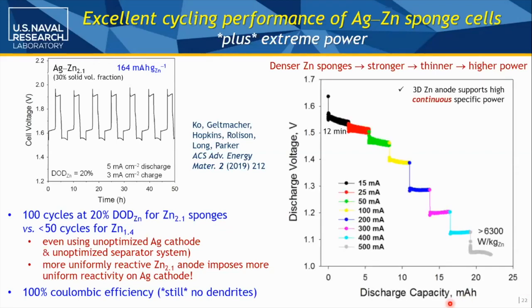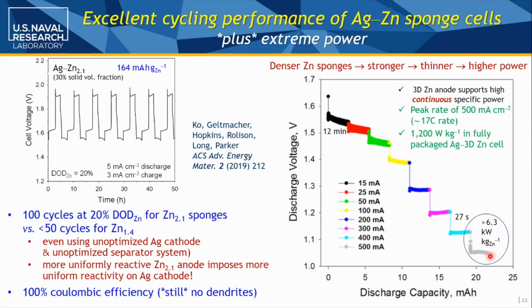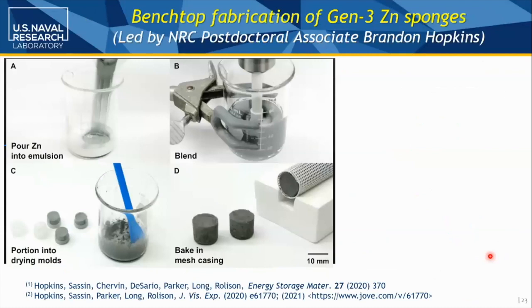So this just shows when you're putting from 15 to 500 milliamps across a square centimeter to a terminal coin cell, you can get up to 6 kilowatts per kilogram of zinc. So at this point, the system's really acting like a capacitor. And as we're making improvements in the zinc, at some point we're not going to be able to talk about silver zinc publicly, because then we start to go on the military critical list of performance.